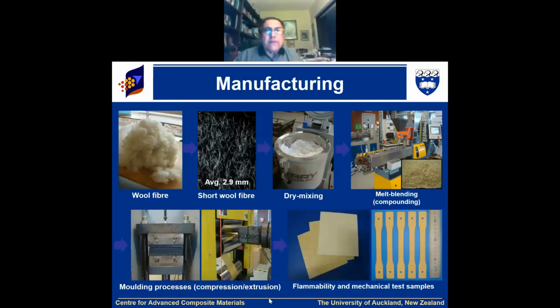Now, very quickly, manufacture of these fibers. I have used only one slide. Like wool can be replaced by wood or jute fibers chopped, and then you can get short fibers. You can prepare a mat, or you can mix it with dry mixing with the fiber, and then you can have a melt blending or compounding. In fact, it's an extruder we have specially purchased, a Milacron extruder for natural fiber extrusion.